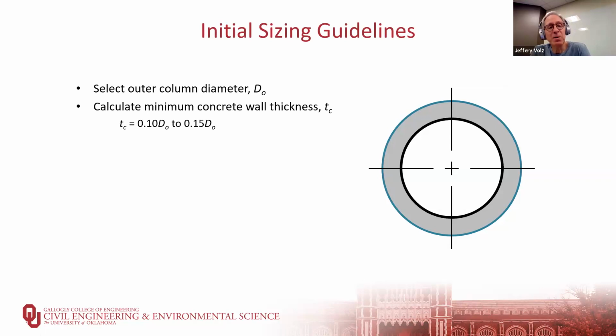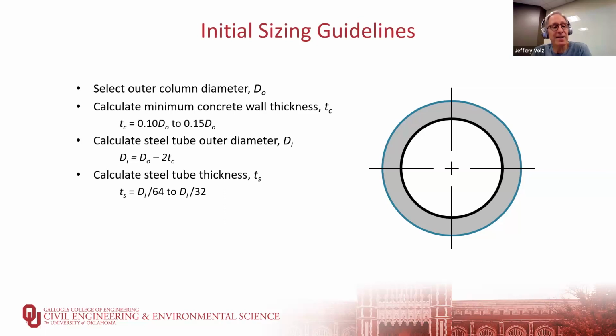The concrete wall thickness is between 10 and 15% of the overall diameter. So if you have an 18-inch diameter column, then you have between 1.8 and 3.6 inch thick concrete section. The steel tube diameter is simply the outer diameter minus twice the thickness. And then the thickness of the steel tube is between 1/64th and 1/32nd of the diameter of the steel tube. At the lower end, 1/64th of the diameter, you have the tendency for more frequent or more common buckling of the steel tube. At the thicker end, that would tend to eliminate some of the buckling, but it increases the cost and increases the weight.